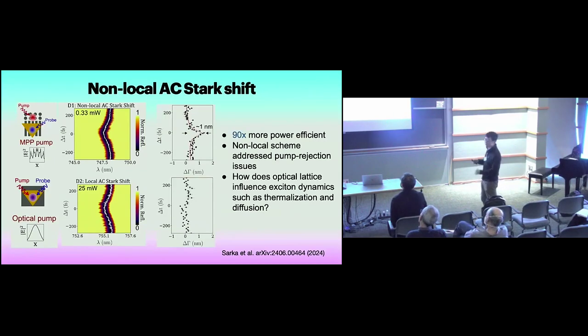This is because the light field is so much confined into a very tiny space around nanometers, so now I don't need very strong power to induce the same amount of shift. So it provides a quite powerful, power-efficient scheme to induce interesting photon-induced physics. And also because we are pumping and probing at different regions, this allows us to do pump rejection. This makes the measurement also a bit simpler.